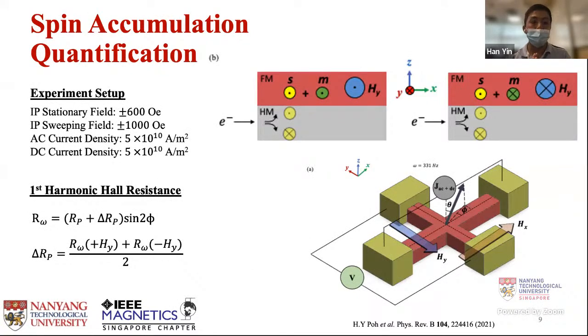So here's the setup of our experiment. First, we apply a stationary positive field and an AC current with a DC offset. In this way, we can ensure the electron spin is polarized in a fixed direction, in this case the plus Y direction. The amplitude of planar Hall resistance is then extracted from the first harmonic resistance.